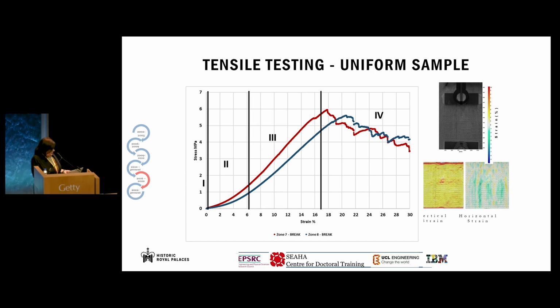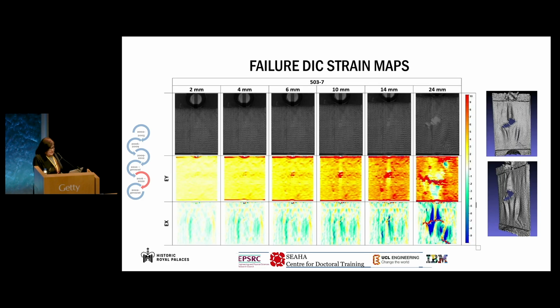And here are all the progressive images of this experiment until failure. So if we focus on the initial stages of the test, we can see that the area with a slight change in the width has been highlighted in the DIC analysis, and this was the area that eventually failed. So this is a very interesting result because even in a very uniform fragment, a very small difference in the weft structure can produce significant change in strain, and that can result in failure after long exposure to changes. On the right, you can see a 3D model Pedro prepared of a fabric after failure to show the 3D effect.